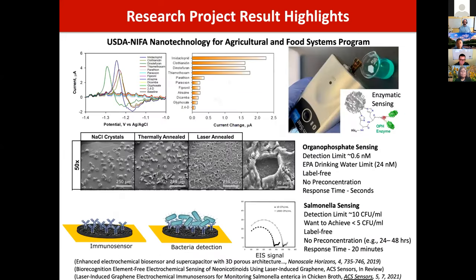And I'll just briefly go over some of the research project results from this. We're able to detect a wide variety of pesticides with high selectivity. Here's a case of looking at neonicotinoids, which have been causing honeybee colony collapse and other environmental impacts. We can even structure the graphene surface to make these pockets or craters, giving even more surface area to improve our biosensor sensitivity. These are just salt porogens that were added and then taken out in the annealing process to give us the surface roughness. We can then add enzymes to them to do organophosphate sensing.